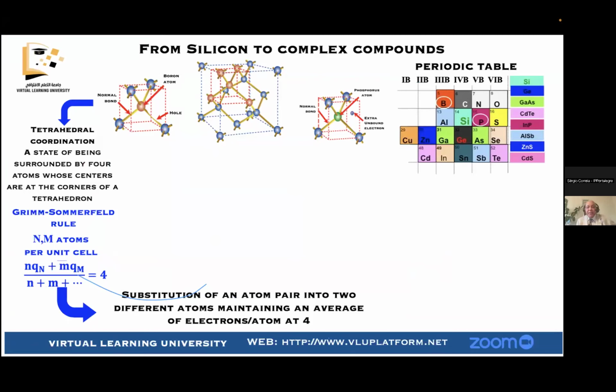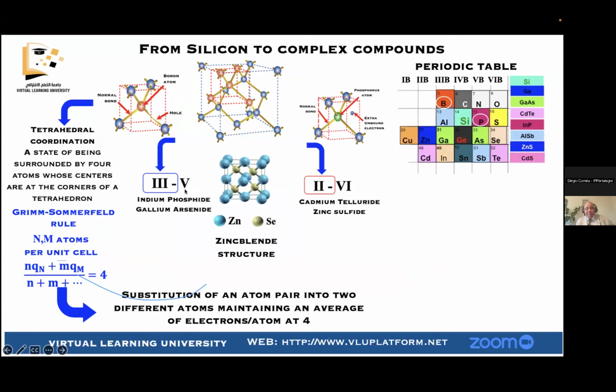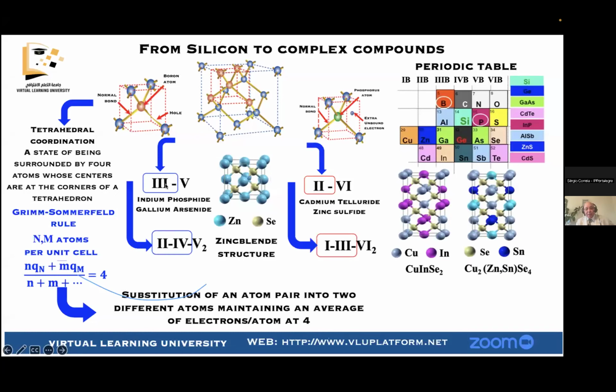So another way is to go from silicon to complex compounds. You can see silicon is a very interesting compound. You can dope it N and P, and you can make a good solar cell with high efficiency, but you can go to the 3,5 compound, as I showed you before, and the 2,6 compound. And you can even go further to the ternary and quaternary compounds. And this is very interesting to think about for solar cells and for water splitting. And I will not go into the detail here.